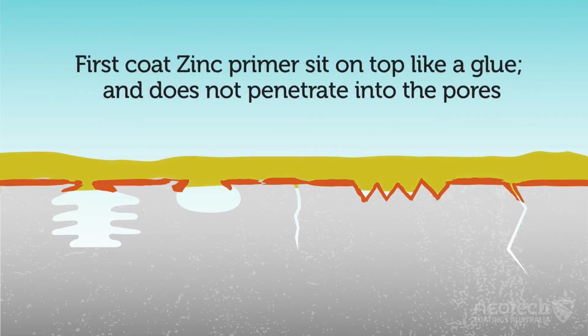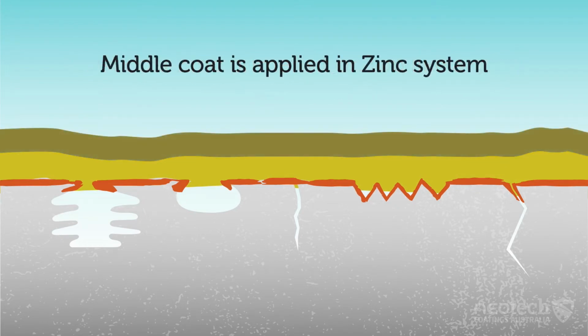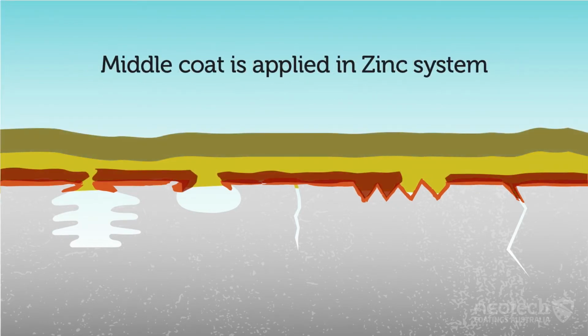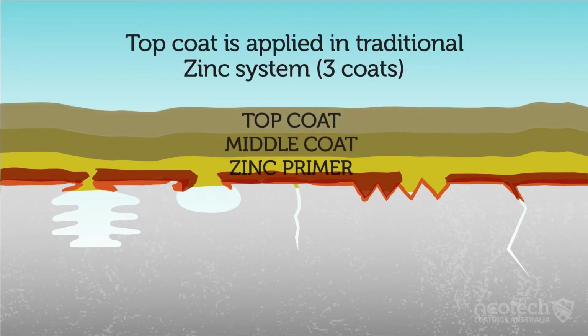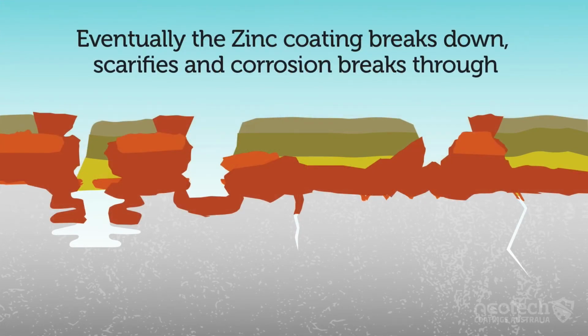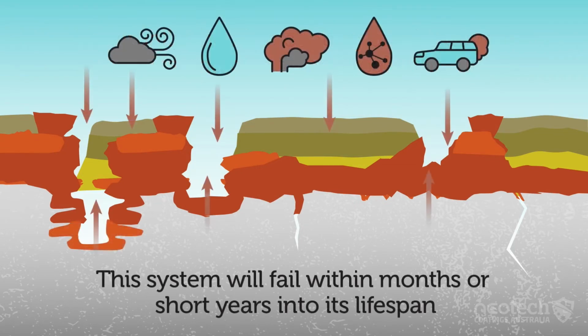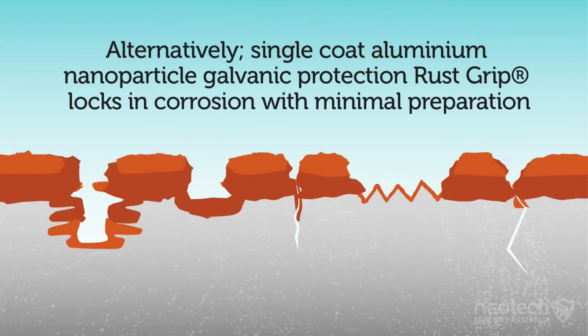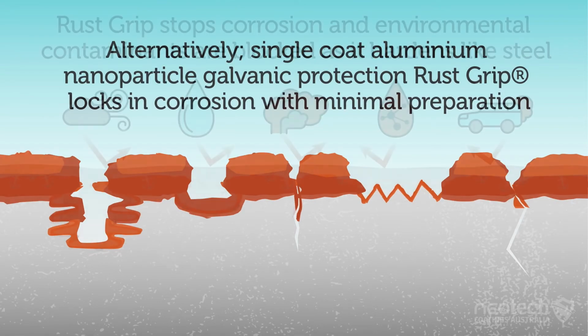When the zinc coating is applied on this bloomed surface, rust, the zinc, being self-sacrificing, begins to allow itself to rust as it is designed to do. There is rust on top of the metal surface, causing rusting again under the entire system of a zinc primer, middle coat, and top coat, 3-part system, and later bubbles on the surface from the corrosion off-gassing. Oxidation and acid rain can also enter and set off corrosion even though the surface coating remains intact. Eventually the zinc coating breaks down and the corrosion is also pushing up from underneath. Within months or a couple of years the system is failing.